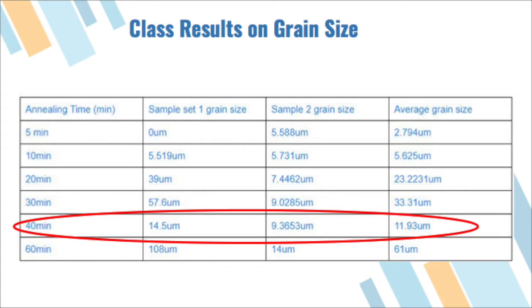Conceptually, the longer these samples are heated, the more likely it is for the grain boundaries to be consumed into larger grains, thus reducing the amount of defects but consequently reducing the strength. As seen, the data follows this relationship between time annealed and grain size until we reach the 40-minute annealing time, where it was measured less. Perhaps this is due to the processing of the sample to begin with, where the metal was purer than previous samples, which would make it harder for the sample itself to recrystallize, thus a smaller grain size is seen. However, we can take a closer look on the next slide by observing the micrograph of it.